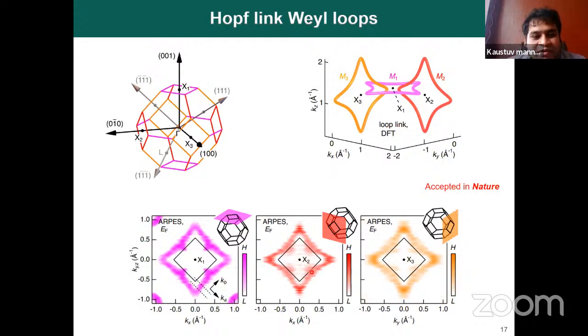Second, when we want to map the other surface, x2, we take the same sample and do an energy dependence, where we vary the energy from 500 eV to 800 eV. Then we get an energy dependence along the kz direction, and we get a component along kx also, and this is how we generate the kx versus kz plot for the Brillouin zone. The same goes for ky also.